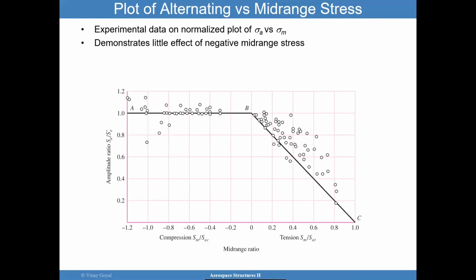So here is another view of that. You can plot the mid-range ratio, mean stress divided by ultimate strength, and mean stress divided by ultimate compression strength. And then you have the amplitude ratio of Sa divided by the endurance limit, the theoretical value, or from the specimen design, that's why there's a prime. And you can see that there's very little effect in the mid-range value when you go negative. All the data has been normalized in this manner to show you the trends. But again, very limited impact on the performance when you go into compression.